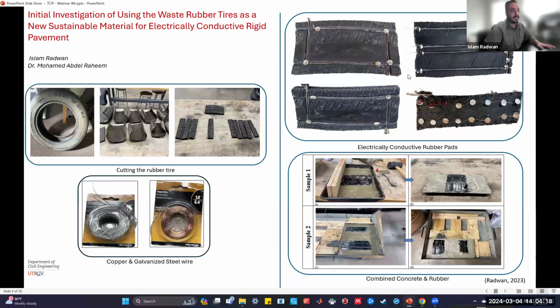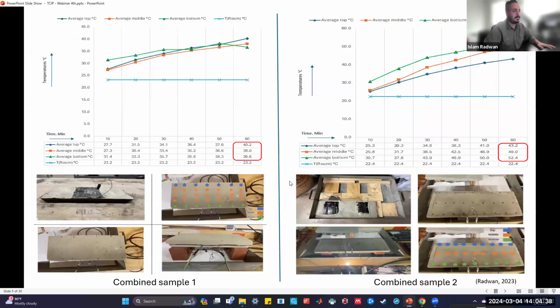Rubber pads. And then after we made sure that these rubber pads can act as a heat source, we embedded them inside the concrete sample. So we made two samples, as we can see here, one concrete sample with one rubber pad and the other with two rubber pads. Those are some of the results that we got.